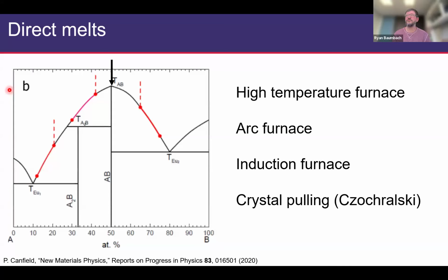And then after you come up with the way that you're going to heat them, you may set up some sort of an apparatus to control the object as it cools. A good example of this is Czochralski, which is where you insert a pull rod into a melt and then slowly withdraw it from the melt. And as that happens, there's an interface between the solid and the liquid where your crystal is forming. Okay, so let me say some things about some of these. Oh, and just to emphasize, it's no good for incongruently melting phases to think about these methods very much.